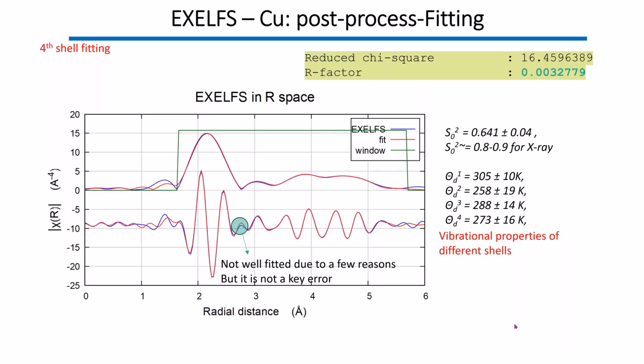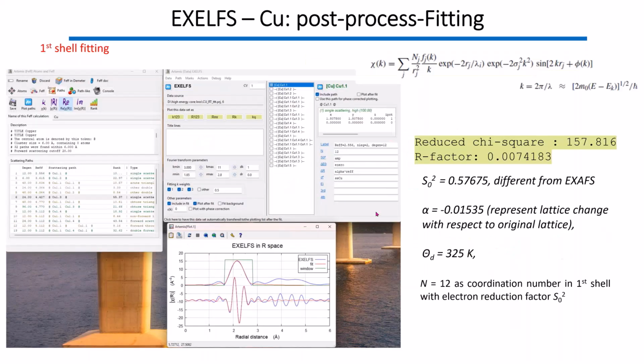Also, one more thing to mention is that for fitting, you should use the fewest possible parameters, and you should not change many parameters. If you change too many parameters to do the fitting, although you can get a very good fit, it's not a physics fit. So one has to be very careful of the fitting itself. Sorry, I'm not trying to say bad things about anyone. I'm just trying to say one should be very careful of the data interpretation, basically.